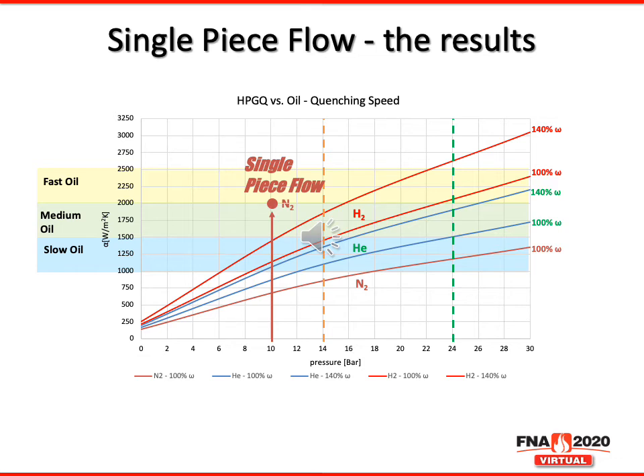And on the vertical axis, we see the overall heat transfer coefficient, if you will. On the right-hand side, on the vertical axis, we see relative fan speeds. But the point is that if we look at 10 bar with a single piece in nitrogen, we see the equivalence to either quenching in helium at maximum speed and pressure, or we reach the boundary between a medium to fast oil quench, again, just in high pressure gas quenching, but with a single piece. This is a significant impact because we aren't exposing the part to a scenario where distortion will be an issue. So we get the hardenability without the distortion.